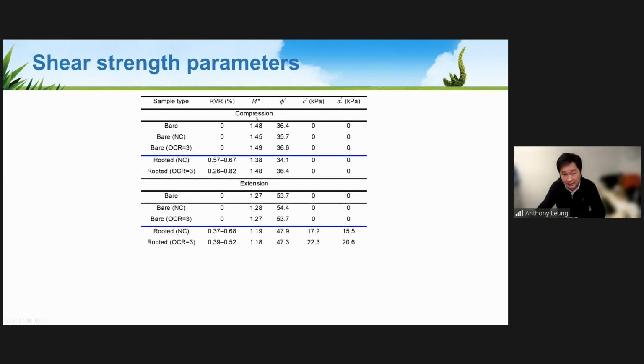Now, if you look at the compression first, you can see that the rooted soil has slightly lower friction angle than bare soil. So I already explained that because of the creation of many soil root interfaces. But if you look at the extension here, the friction angle also reduced for the rooted soil, but the cohesion increased very significantly. You can see from 0 for the bare soil to something like 22 kPa for rooted soil in the extension, right?